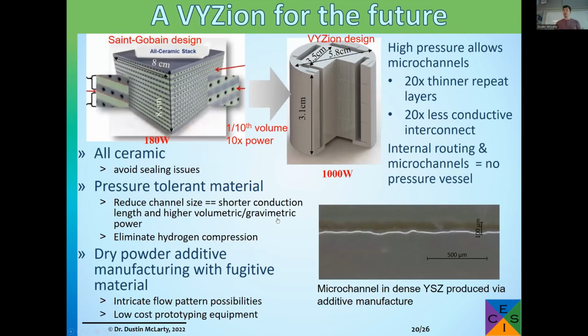And we want to produce a design like this. So the picture on the left here, this is a Saint-Gobain design, and they did this via extrusion. They made a slurry, a very thick paste, extruded it with these holes, and then cut it into rectangles and stacked them together before they co-fired it. We want to do the same co-firing, but we want to print the layers with dry powder on top of each other so that we can have all of the gas routing internal to the ceramic part.